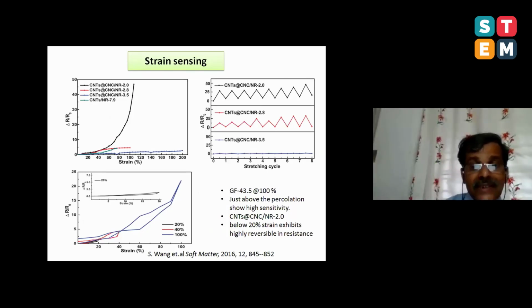Nanocellulose and CNT in rubber matrix. Look at this, strain sensing followed by looking at the conductivity. You put the mixture in natural rubber and you stretch it. Look at this, a combination of nanocellulose and CNT together. You see the resistance increases as you stretch, because when you stretch the rubber, the network is destroyed. That is why you have an increase in resistance.